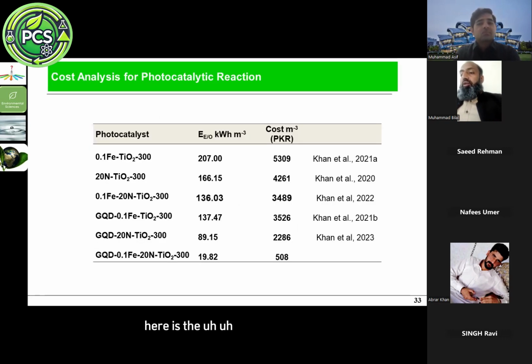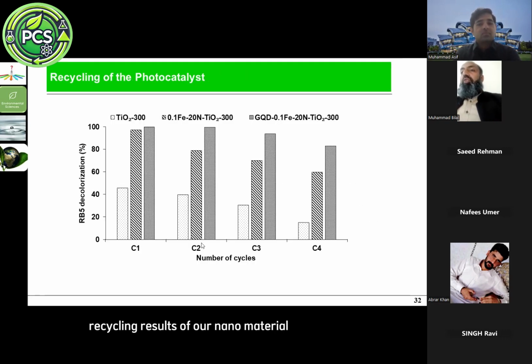Here is the recycling results of our nanomaterial. We are showing here only 3 nanomaterials. Till the fourth cycle, almost 80% of our finest material was showing above 80% decolorization capability till the fourth cycle of the regeneration. However, the decrease was obvious with titania, and then with the iron nitrogen titania, and finally the lowest decrease in the decolorization capability of our material was observed till the fourth cycle.